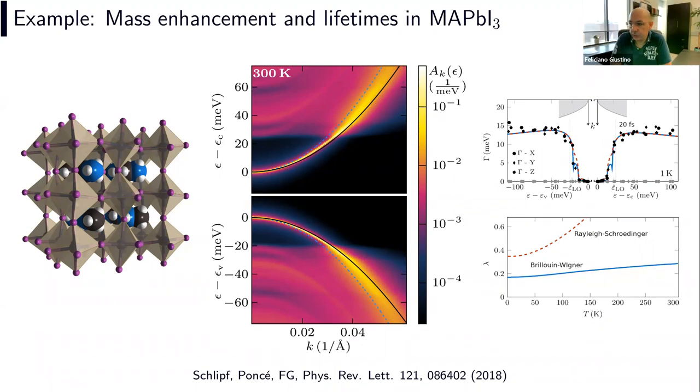So I think there are two different things. When people talk about long-lived carriers in this compound, what they refer to is that when you create an electron-hole pair, it takes a long time before recombining. While in this case, what these lifetimes are is, for example, imagine an injection: you're transporting an electron and you want to know how long it stays in that state. So it's more like a scattering lifetime. There is no concept of recombination. That requires looking at the band-to-band recombination and the short-lived hole, which goes through defects. And that's basically another piece of physics. Okay, sounds good. Thank you very much.